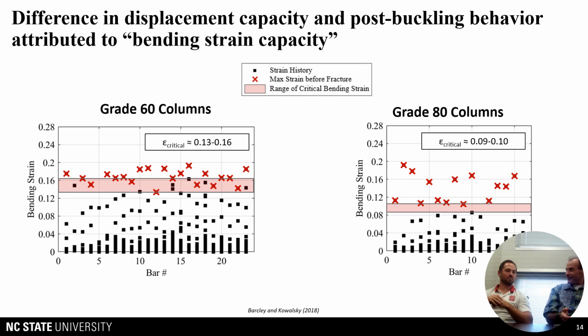And then Leo, you did that for your tests. And yeah, like we mentioned before, we saw that one of the bars buckled in the grade 60 tests, the conventionally reinforced. It had a couple of different displacement cycles, and we're trying to look at why this happens. So we did the same thing with the grade 80 columns, and I think there were 16 bars in each of these tests. Right. So you only had a couple of bars on the extreme fibers that are actually buckling, which is why you don't have a vast wealth of data. We just have the data from the bars that actually buckled.